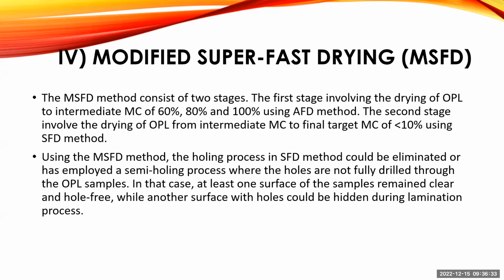So the modified super fast drying method consists of 2 stages. The first stage involved drying oil palm lumber to an intermediate moisture content of 60, 80, and 100 using forced air drying method. The second stage involved drying oil palm lumber from intermediate moisture content to a final target moisture of less than 10% using the super fast drying method.